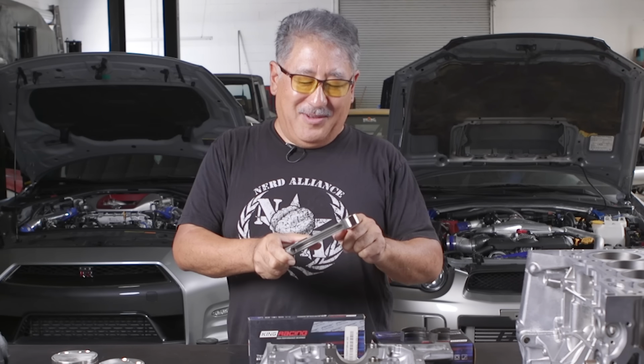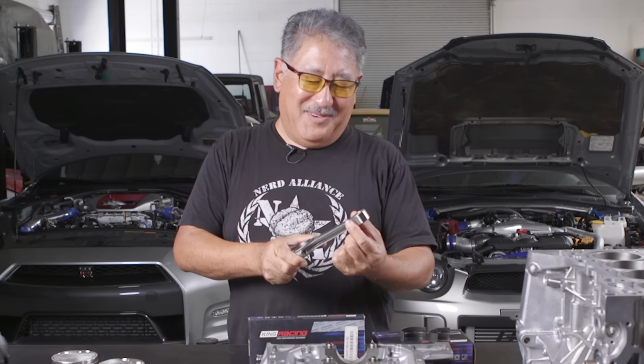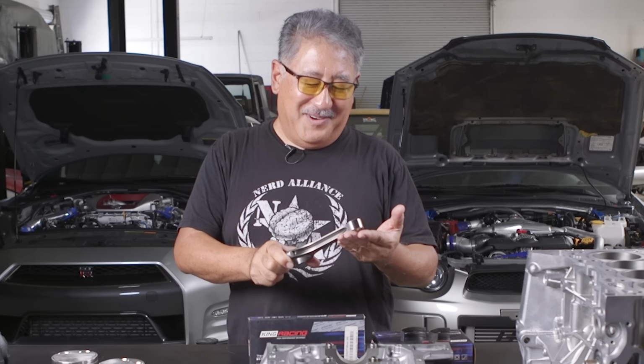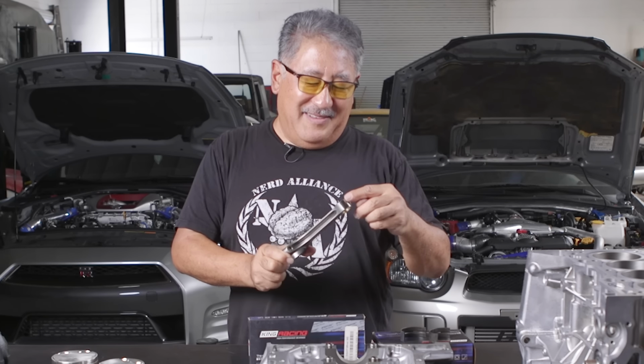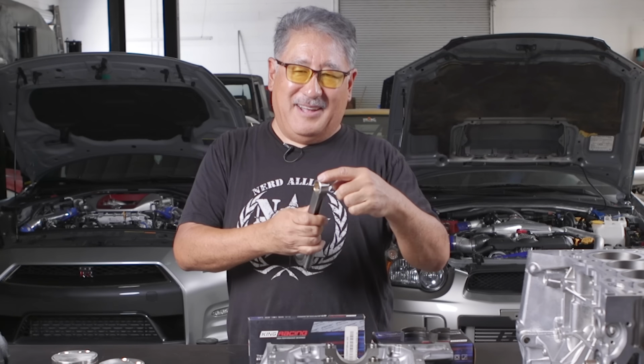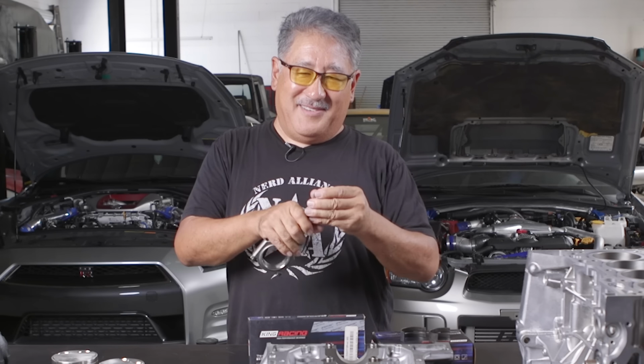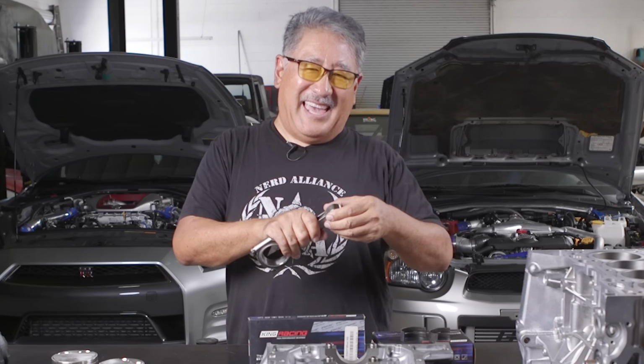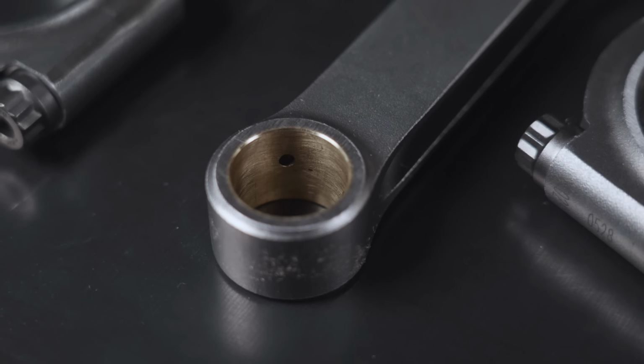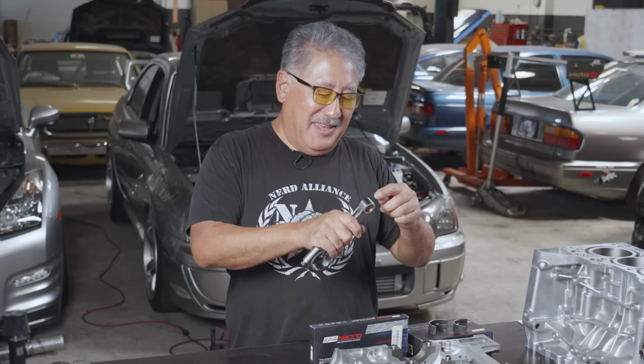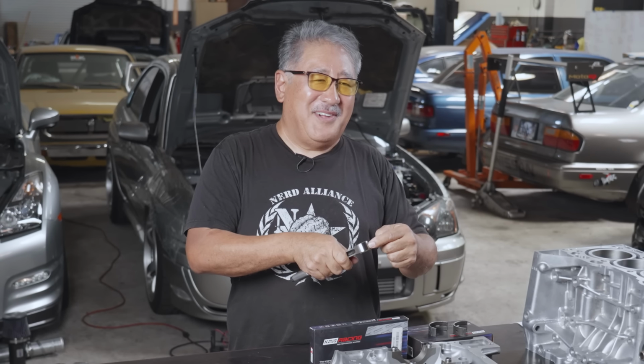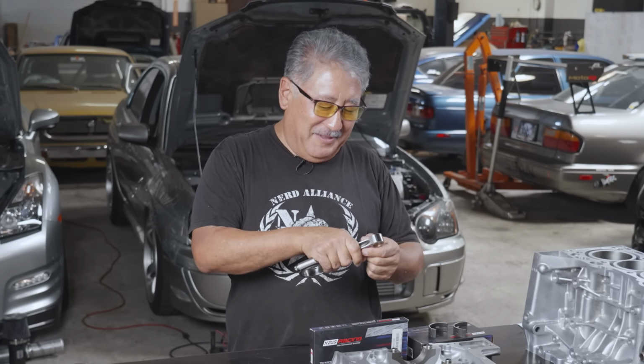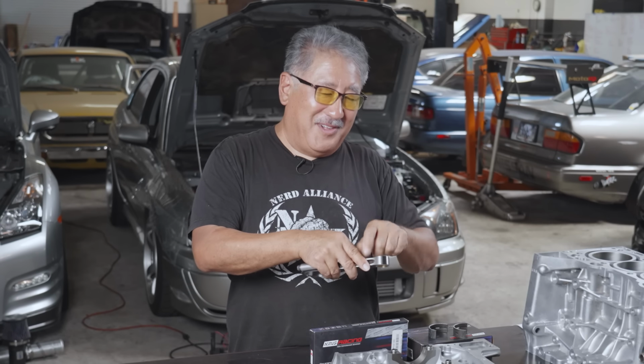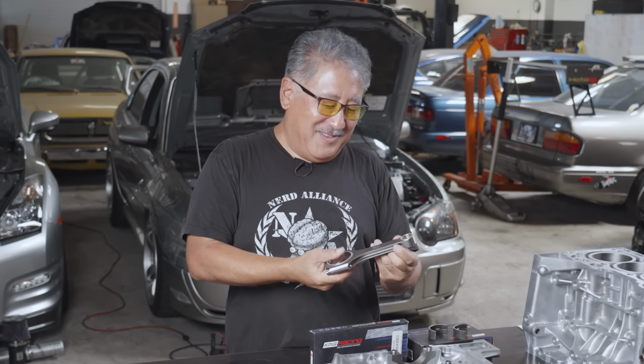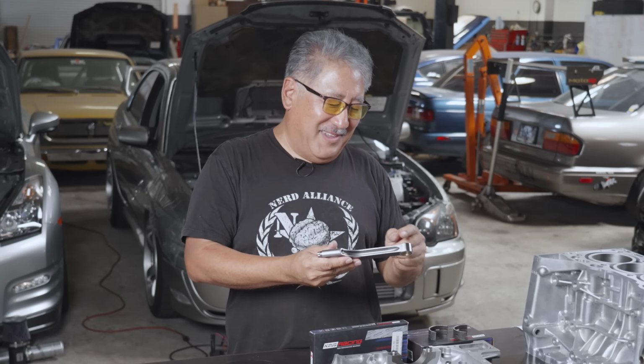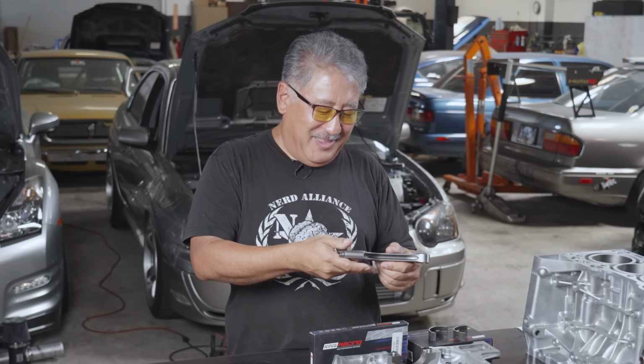The reason why they're having the oiling holes on the sides is important, or why it could be better, is this is a part of the rod on the top that's pretty highly stressed, because the pin wants to yank out of the top of the small end when it's accelerating. And when you remove material here, that creates a weak spot. So there's a lot more material around the base of the small end. So having two small holes can be better than having one big one at the top.